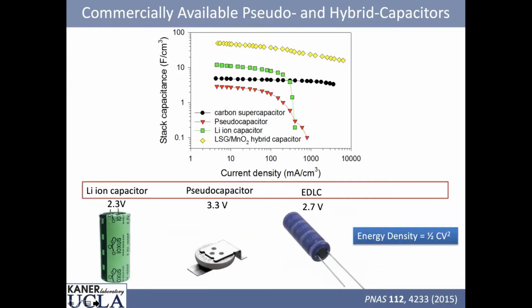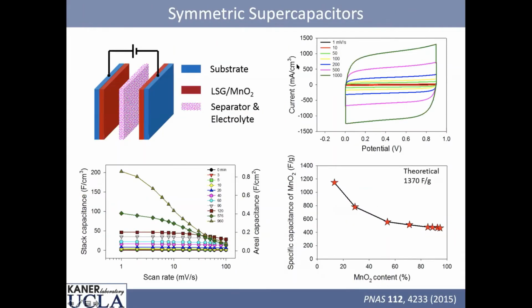And in fact, here's the result. If you look at a current potential curve, you get these beautiful rectangular waves. I'm going to focus at the bottom right. This is the specific capacitance of MnO2 versus the amount of MnO2. In theory, manganese dioxide could have 1,370 farads per gram. Now you can't get that because it's an insulator. But if we put 10% MnO2 and 90% graphene, we can get around 1,200 farads per gram. So we can get most of it.